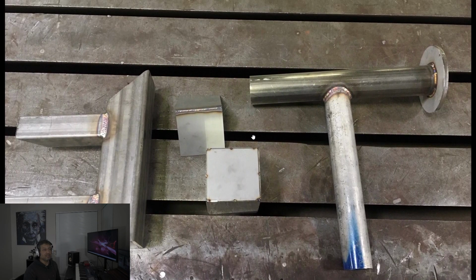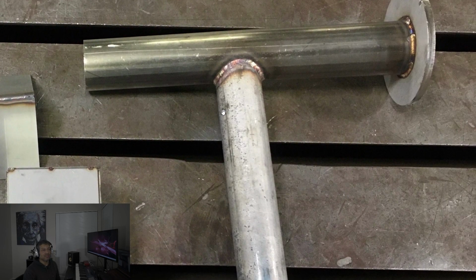And last but not least, we have round stuff. You're supposed to fit this up at 90 degrees, so you can fit something up properly without it bowing too much to the left or the right. Things that are round are typically more difficult. I believe this pipe is schedule 40, so it's pretty thick, and you can pump a lot of heat in there. But what he's looking for is a consistent bead. The pipe is relatively small for this industry, about 1.25 inch diameter, but it still requires you to move quite a bit. So yeah, it's a really good test.